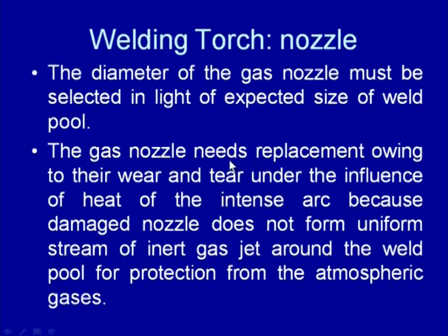The gas nozzle needs to be replaced due to wear and tear under the influence of the heat during welding. We know that the nozzle is very close to the welding arc, and the high heat generated during welding damages the nozzle tip. Once the nozzle tip is damaged, it loses its shape and becomes unable to form a sound jet of shielding gases around the arc to protect the weld pool.